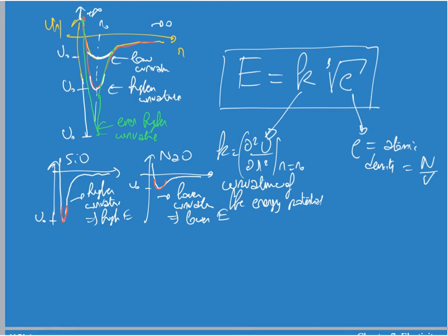The second thing here is about the number of atoms that you have. Here, this term tells you the density. It tells you that the more atoms you have per unit of volume, the higher will be the Young's modulus. This comes from the fact that the more atoms you have within your system, the more bonds they will create per unit of volume. So the more little springs per unit of volume you will have in your glass. So if you have more bonds, more little springs, then this is also going to increase the Young's modulus.